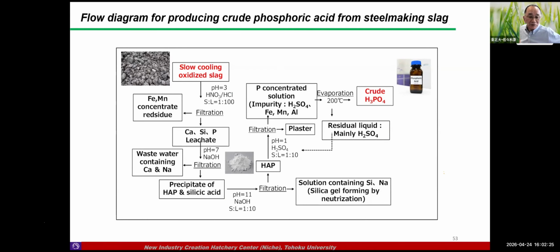Several works were carried out to recover phosphorus from steelmaking slag. This was done by Professor Kitamura's laboratories. You can see that starting from steelmaking slag, it finally goes to crude phosphoric acid. So many steps are needed that it becomes very expensive. Producing phosphoric acid is easy using phosphate ore. If we recover phosphorus and produce phosphoric acid from steelmaking slag, the cost is almost 10 times higher. So there is no way to apply it. Definitely, we have to find a very effective and economical recovery system. Very challenging.